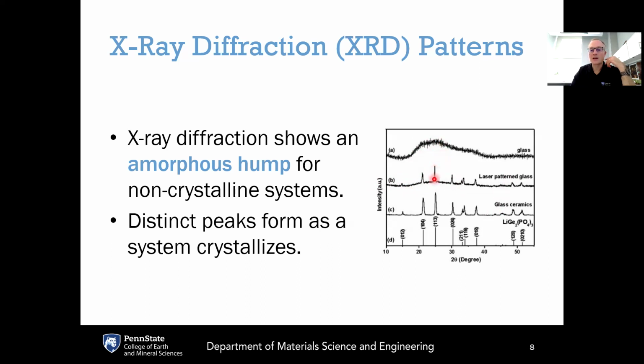And the balance between the sharp peaks versus the amorphous hump is governed by how much of the volume fraction of your material is crystal versus still in the glassy phase. So if the material is mostly glassy with just a small amount of crystals, you will see something that looks a lot like this amorphous hump, just with a few small peaks on it. As the crystals grow over time, the amorphous hump becomes less and less, and the crystalline peaks become more and more well-defined and become higher in intensity.